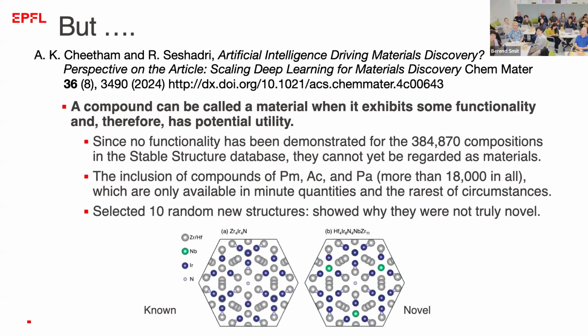So let's first show his main argument. If you look at inorganic materials, you'll have things like niobium and hafnium and zirconium, and those metals are very similar, so every inorganic chemist knows that you can exchange them. For example, what they did is they selected 10 new materials and tried to identify whether those materials were truly novel. And this is a typical example where you can already see that the main difference is this green dot here in the crystal structure. And that is typically one of those elements you can easily exchange. So for an inorganic chemist, this is not really a new material, but more problematic is it will also be very difficult to synthesize them.